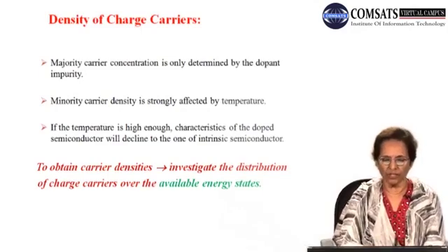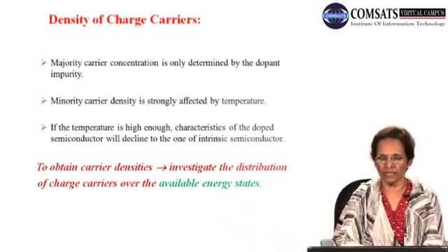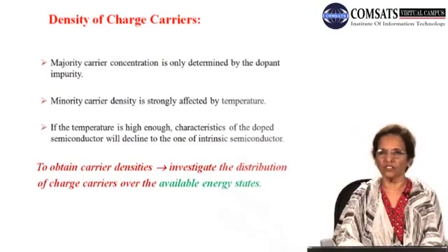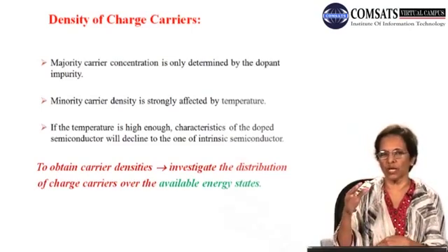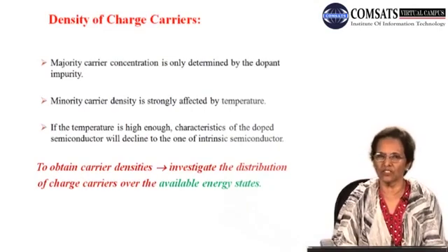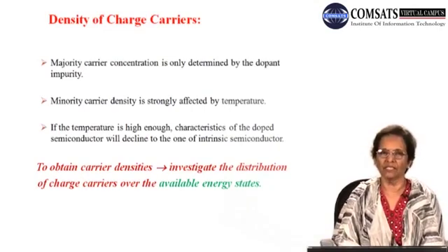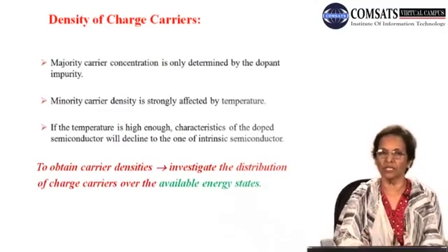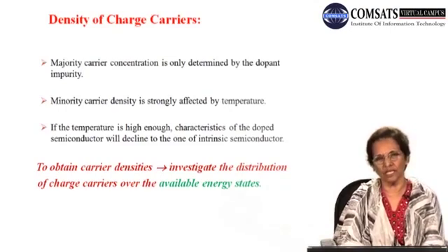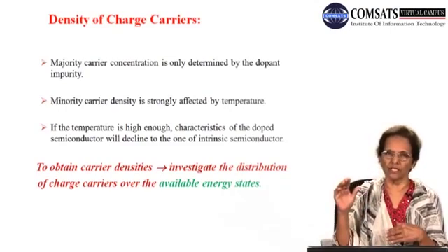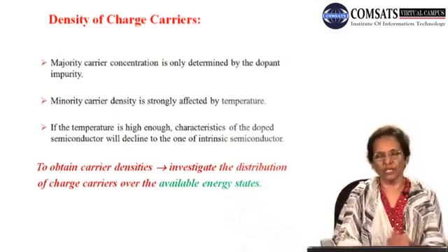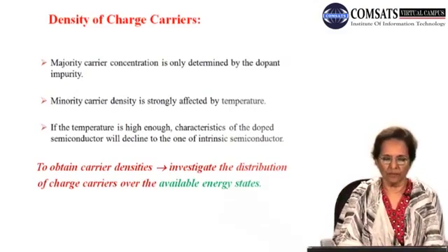Thus minority carrier concentration is strongly affected by temperature, unless we increase the temperature so high that even the majority carrier concentration gets affected. Then the doped, extrinsic material would start to behave as an intrinsic material again, but that takes place at a very high temperature, which I have explained at the bottom of the transparency.